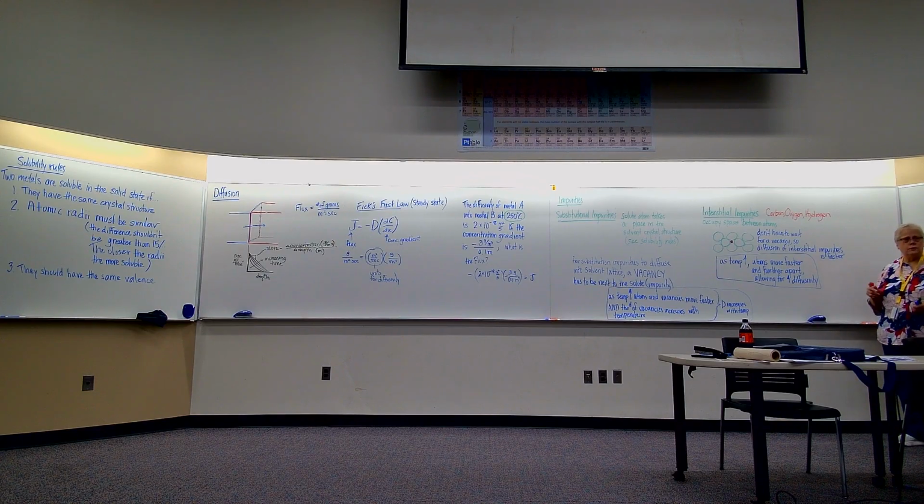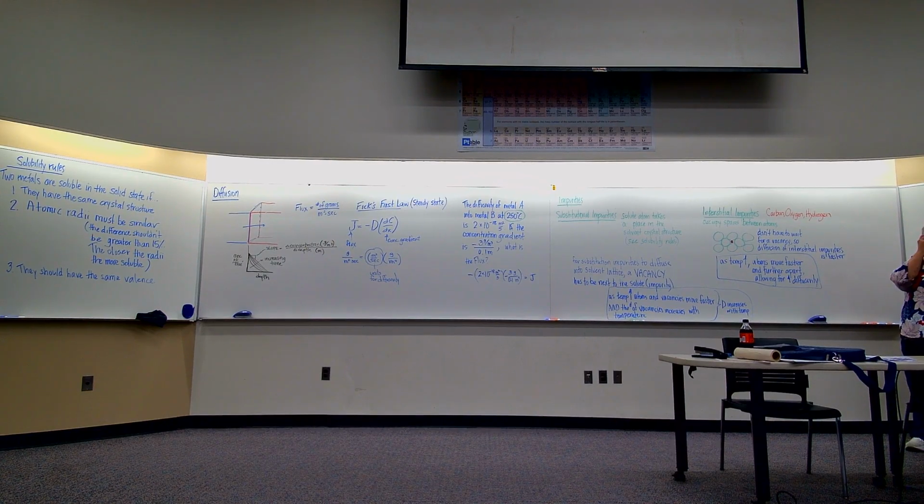But those three for sure. For most metals, hydrogen and oxygen are bad if they've diffused into the metal. They cause it to become brittle. Carbon is good. Carbon makes the metal stronger. So this is how carbon finds its place among iron atoms in steel.